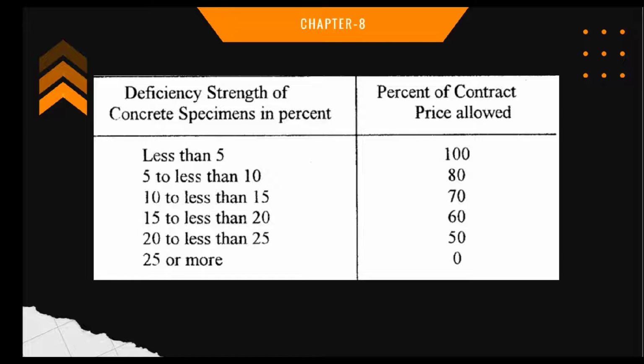Concrete which does not satisfy the above criteria may be rejected unless the contractor could provide evidence, by means of a core test, that the quality of concrete represented by the failed test result is acceptable in place. At least 3 representative cores are taken from each member of concrete area in place that is considered deficient. Core location should be determined by the supervising engineer so that there will be least impairment of the strength of the structure.